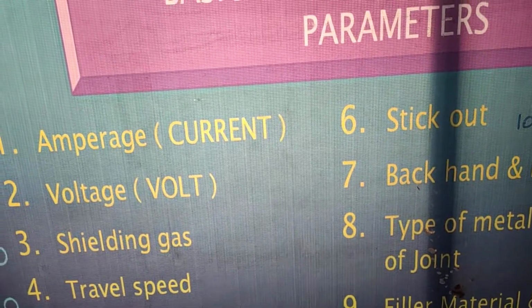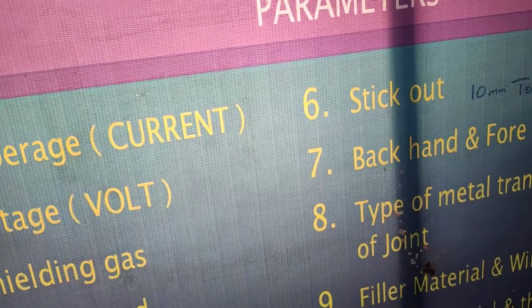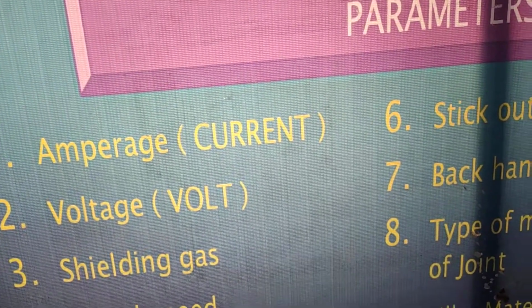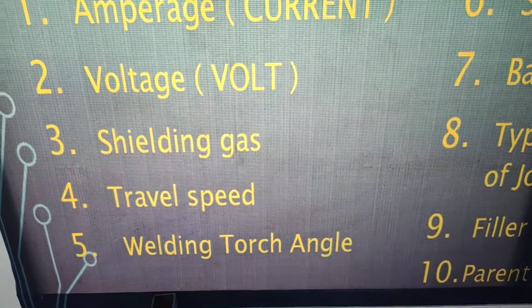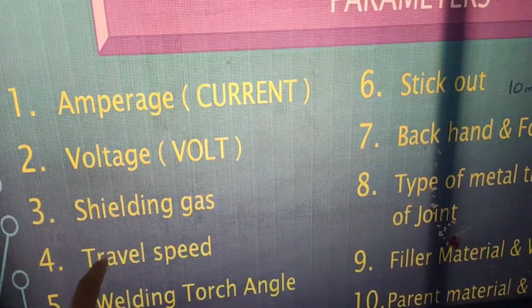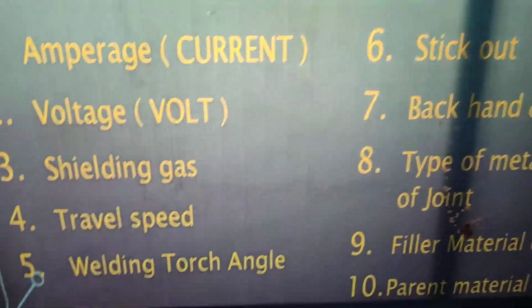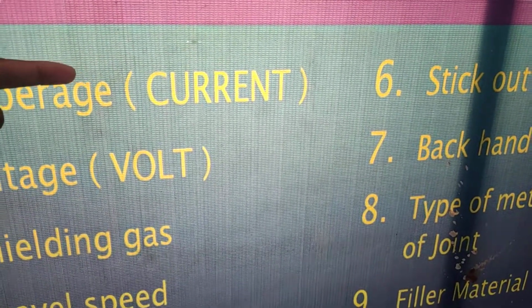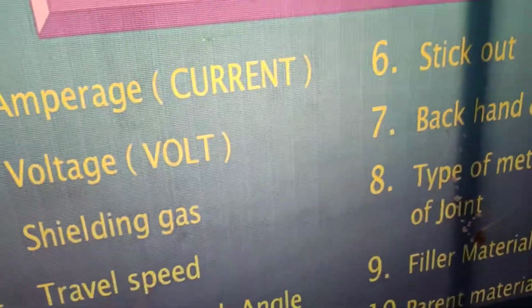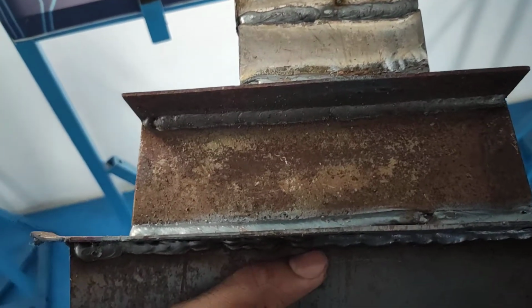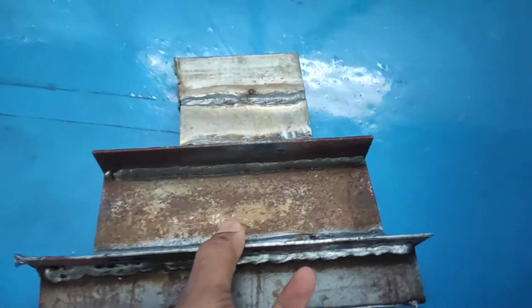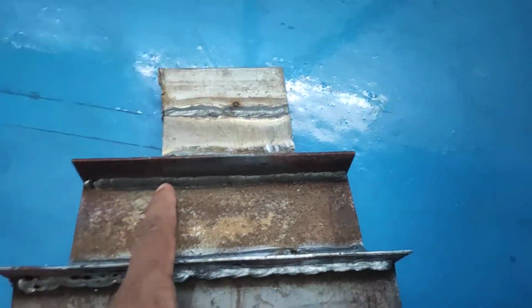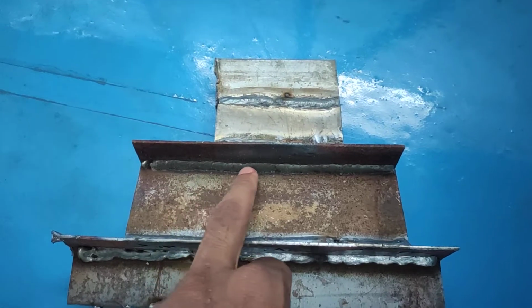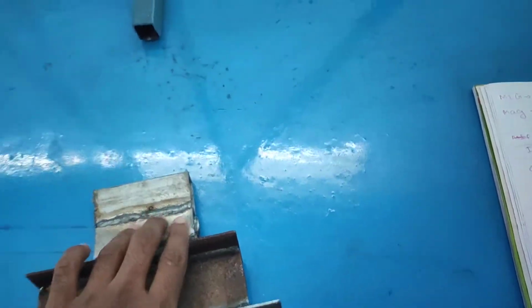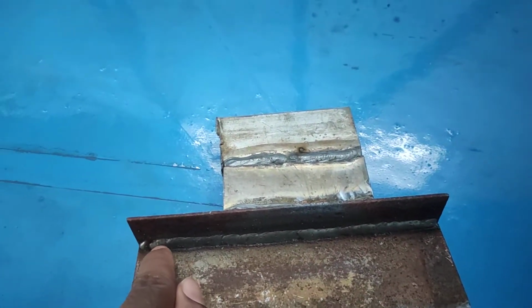In MIG welding, GMAW welding, the proportion for most welding is argon 80%, carbon dioxide 18% and oxygen 2%. Oxygen we can't use more than 2%. If we use only argon as a shielding gas, the weld layer is spattery, like a narrow line. It doesn't bond tightly, so we can't use argon gas alone. For example, this is the usage of the mixture gas: argon 80%, carbon dioxide 18%, oxygen 2%. If we use this mixture, it looks perfect. But if we use argon gas only, it's not like this. Its border is like a narrow, single line. So we can't use single gases.